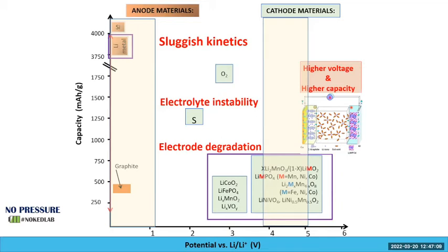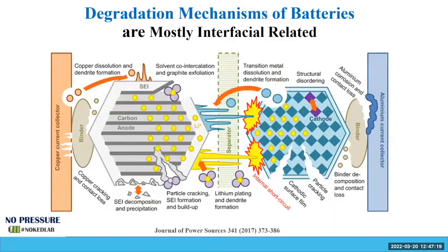Yeah, so the amount of cations you can put in per gram of material is even higher for silicon when you're comparing it to metallic lithium because of density. The challenge, however, is also related to the amount of silicon. The more you put in, the more you are expanding your material. If I take a grain of silicon and lithiate it fully, the volume change is 300%. And then when you are shrinking it back, it is cracked.